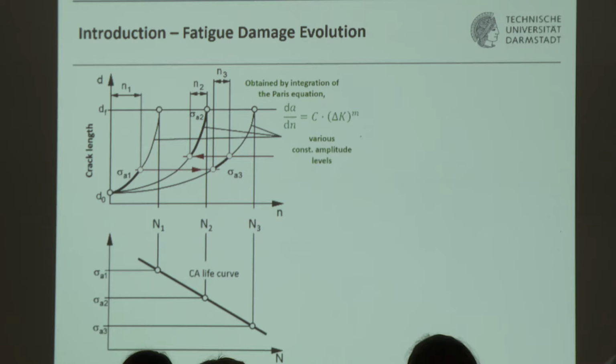And the simple idea is to go to the simple Paris-Erdogan law of crack growth and perform crack growth calculations. And if you do so, and start at an initial crack length, you get the well-known crack growth curves. And if you apply a high amplitude to your structure and to your material, you end up with a short life to fracture. And fracture is defined here as a given and constant length of a crack. Here in my application, it's a crack initiation of a millimeter or something like that.